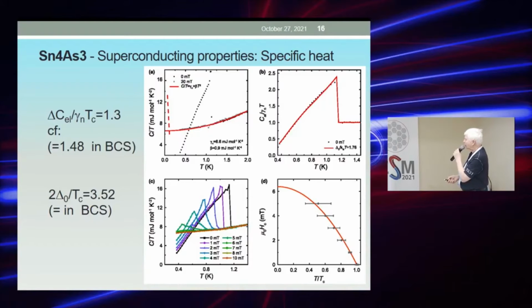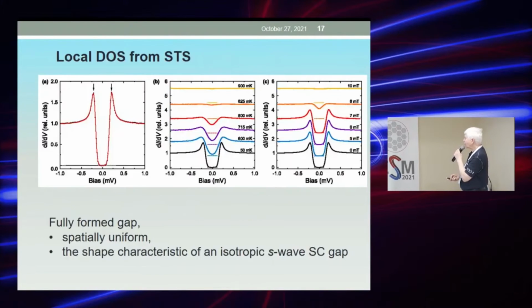I didn't put a plus minus sign here, but it is just like a textbook value. We also tried to see anything interesting in the local density of states by scanning tunneling spectroscopy, doing this down to 50 millikelvin. And we find a fully formed gap, which is spatially uniform, no nodes, and the shape is characteristic of an isotropic s-wave superconducting gap.